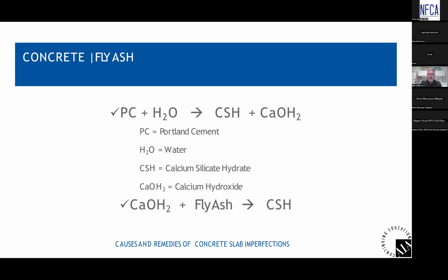So from a pure chemistry standpoint, fly ash is used to densify concrete. It creates a tighter, denser mix. But it's very critical how much fly ash is added into concrete, because it depends on how much of the calcium hydroxide is in there as a result of the concrete's chemistry.